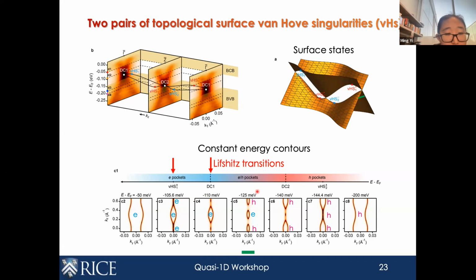If you go down, you can also go down to an energy where the Fermi pockets of the hole pockets and the electron pockets give rise to very good nesting conditions. And you can imagine this would be a really interesting regime to look for any nesting-driven instabilities. Keep going down. The next energy that's interesting is the lower Dirac point. This is when the center electron pocket changes character into hole. And then the next energy is the bottom pair of Van Hove singularities, and this is when the three pockets merge together and then eventually become a single open large hole pocket, which is the reverse of the initial electron surface.